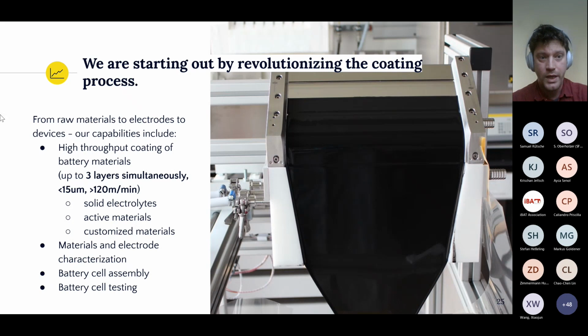I mentioned this earlier, so we are starting out with the coating process. Right now, we have the capability to coat 3 layers simultaneously. We can produce layers that are less than 15 microns in thickness, and we can coat individual sheets at 120 meters per minute or faster. This is all still in the lab scale. We're preparing the rollout for roll-to-roll manufacturing, but this is what we can do at our own lab at the moment.